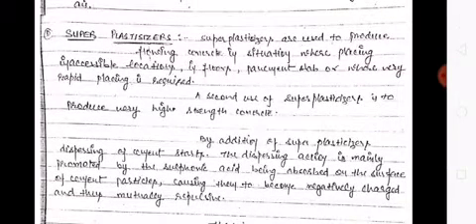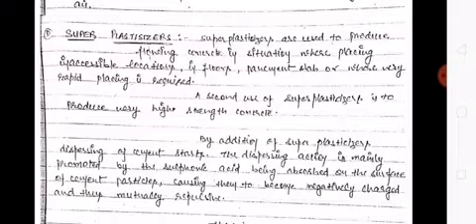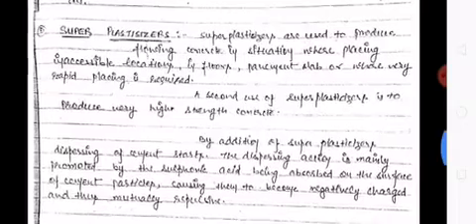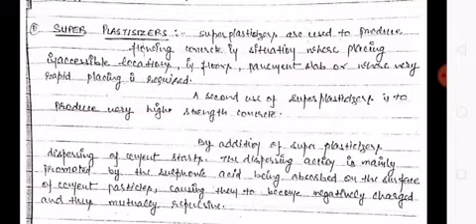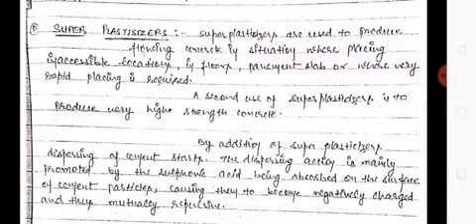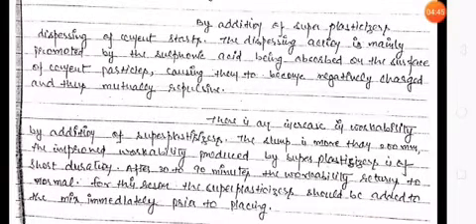Super plasticizers are used to produce flowing concrete in situations where placing is in inaccessible locations, floor pavement slabs, or where very rapid placing is required. A second use of super plasticizers is to produce very high strength concrete. The dispersing action is mainly promoted by sulfonic acid being absorbed on the surface of cement particles, causing them to become negatively charged and thus mutually repulsive.